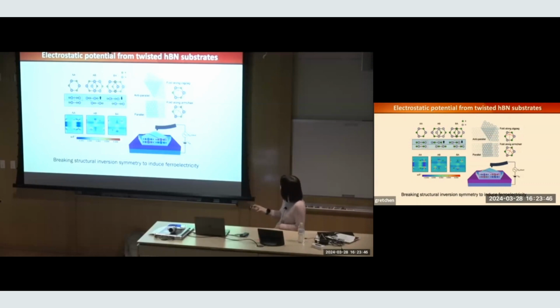hBN is a high gap insulator. There's no charge transfer, but there will be slight charge redistribution. This is a DFT calculation. You can calculate precisely how big the polarization is, and it matches our measurement very well. I'll show you that shortly.